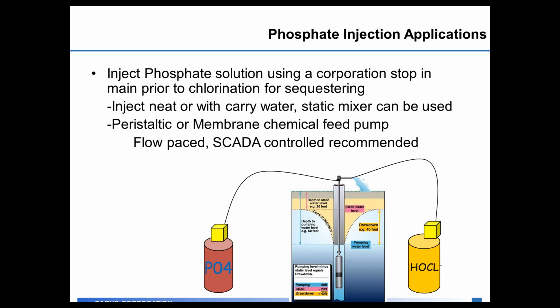Phosphate injection applications: one of the easiest things to apply is phosphate. You want to inject your phosphate solution using a corporation stop in the main prior to chlorination, specifically if you're looking at sequestration. In the case of groundwater, you're always going to want to apply the polyphosphate or the blended phosphate prior to your chlorination, because chlorination is going to be your oxidation. So it would drop the iron and manganese out of solution.